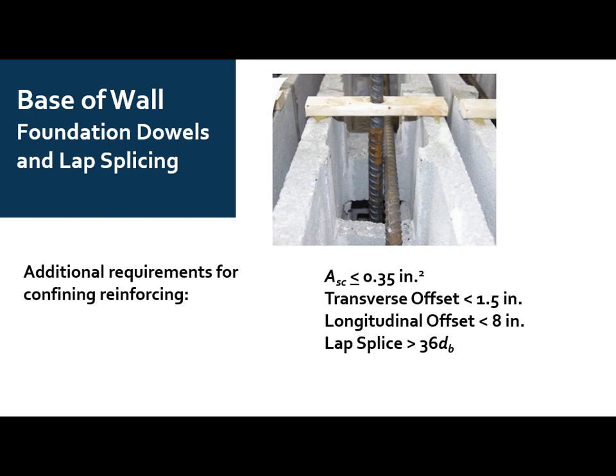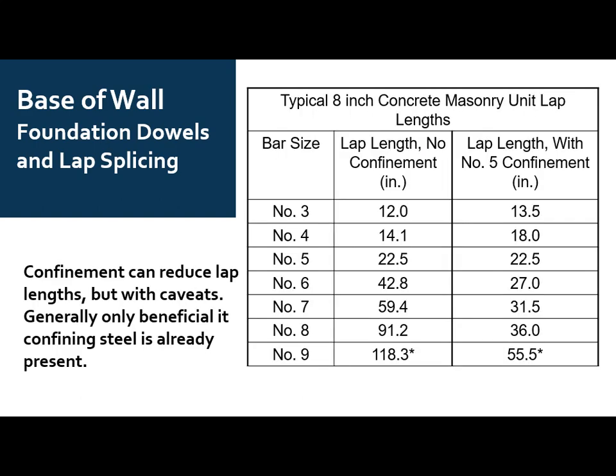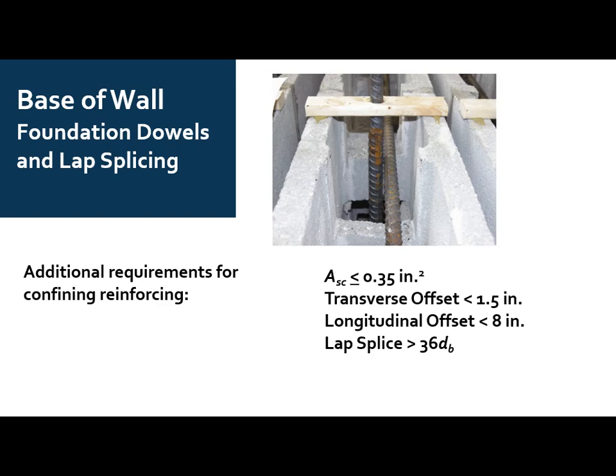The next one down, the longitudinal offset, basically says that from the end of the lap down 8 inches is where that horizontal reinforcing steel has to be placed. So we can't have it cross at any location across our lap. It has to be at the ends of the lap splice. And as I alluded to when we looked at the numbers in that previous slide, our minimum lap length can't be less than 36 bar diameters, which is why we see things bump up for these small bars. There's that requirement of 36 db that kicks in for these small bars, because otherwise you'd end up with something even smaller than that. And what that 36 db is intended to preclude is that pull-out failure. We don't want a bond failure from having such a short lap length, where it just debonds from the grout and you're left with a smooth bar or a smooth hole in the middle.